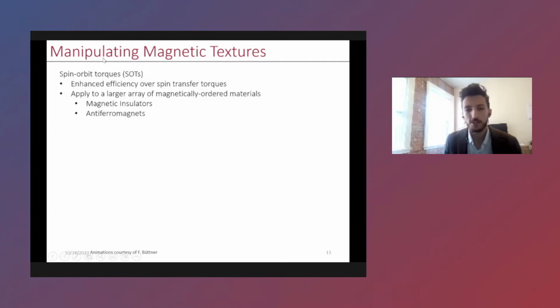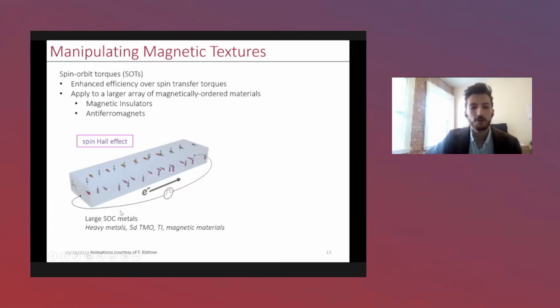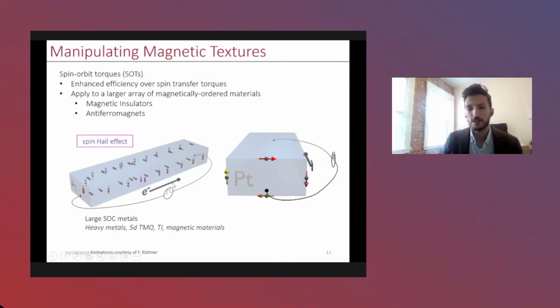And I'll just remind you, this is a way where in heavy metals, 5D transition metal oxides, topological insulators, and other large spin-orbit coupled systems, and even some magnetic materials, you can pass a charge current in these materials, and the spins of the different charges actually get separated or sorted depending on their orientation. And so effectively, you can take a charge current and turn it into a transverse spin current, which has angular momentum. This is more easily seen by the cross-section here. And so this is a more efficient process than using something like a spin transfer torque.